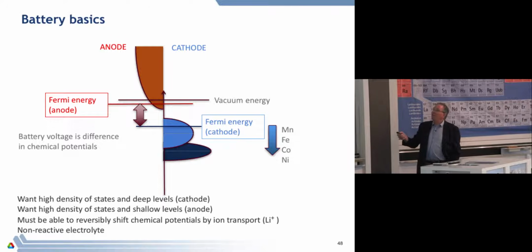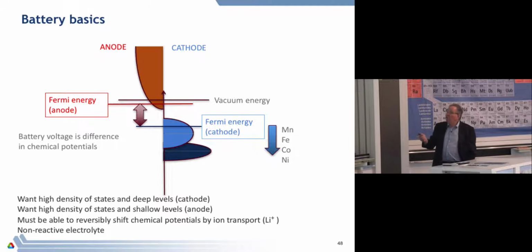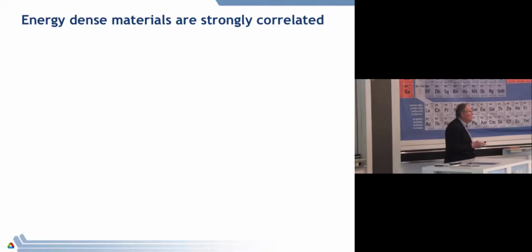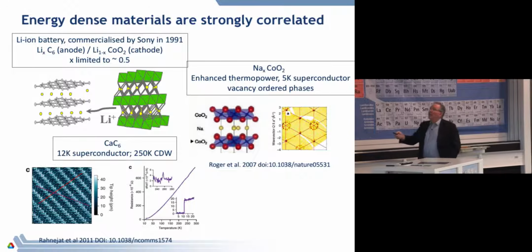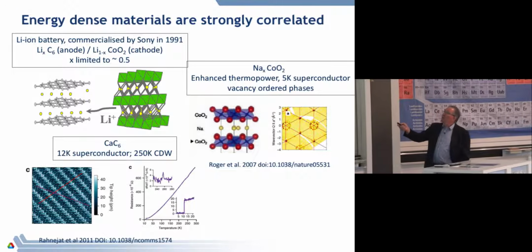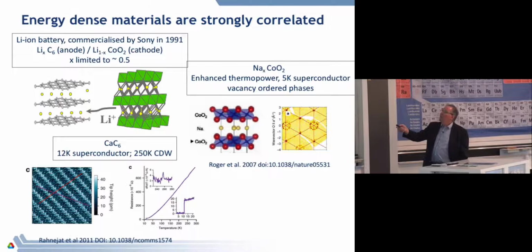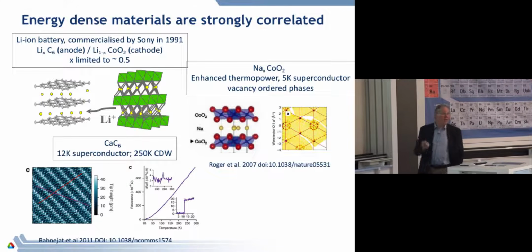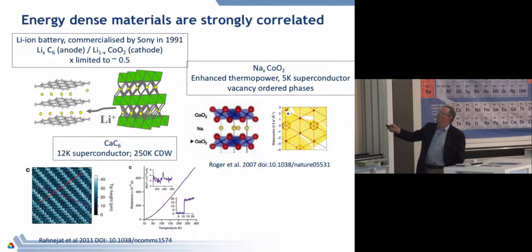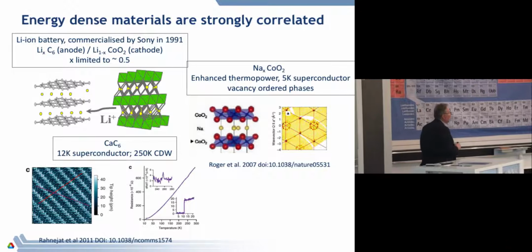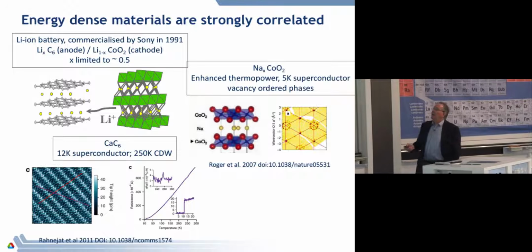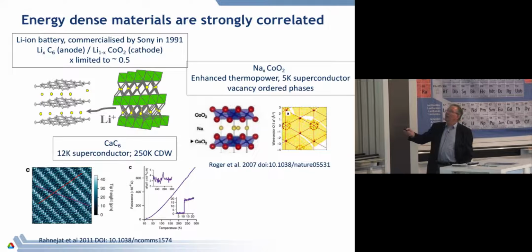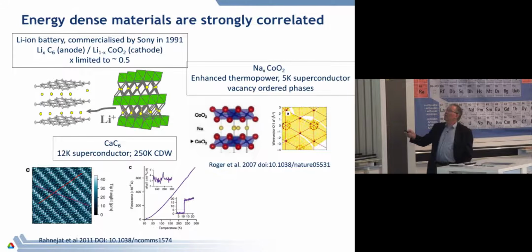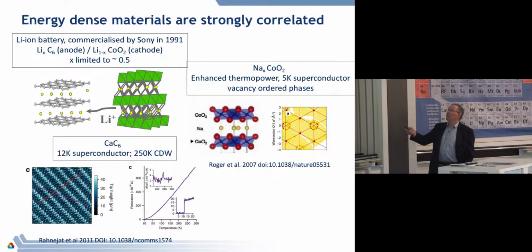So you would like things which had a tighter density of states, or you'd like to put different kinds of ions in here. Okay. So that sort of gets you to the materials that we have now. So, as I say, the commercialized battery in 1991 from Sony is based on lithium cobalt oxide on the cathode. So that's not a perovskite, but it is another layered oxide. And the lithium shuttle in and out of here, and they shuttle in between the layers of graphite. And you can't get further than LiC6. And you can't get much more than a half of lithium cobalt oxide.